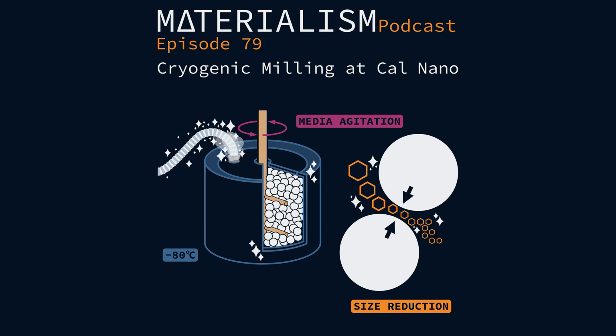So that's kind of the point when we're talking about taking these elemental materials together and combining them. It's mechanical alloying of, let's say, aluminum, titanium, tungsten, niobium, all these different materials. You can combine them and make a fully homogeneous, mechanically alloyed part. And we've done this with, like I said, aerospace alloys. We've combined it with a ceramic and other metals, and we've been able to increase the strength by 2-3 times through the cryomilling process.